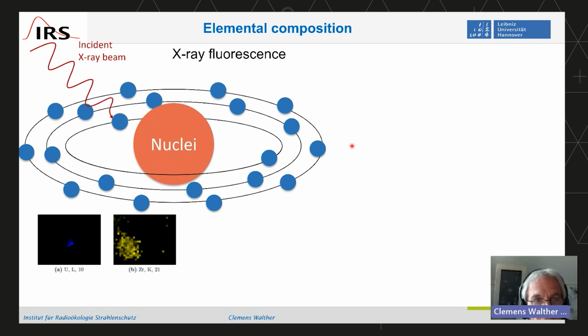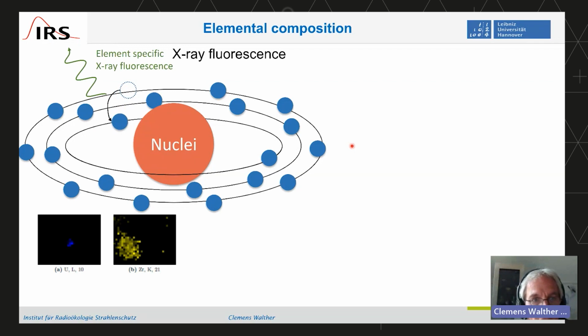So X-ray fluorescence, you have an incident X-ray beam, and you ionize, so you get some electrons emitted from the shell, and then you get electrons from the outer layers filling up that gap, and by that way emitting characteristic X-ray fluorescence. And this X-ray fluorescence can be the basis of a mapping. And here in this example, you see that there's some uranium in here, and that there's also some zirconium in here, but they're not correlated when it comes to the location.